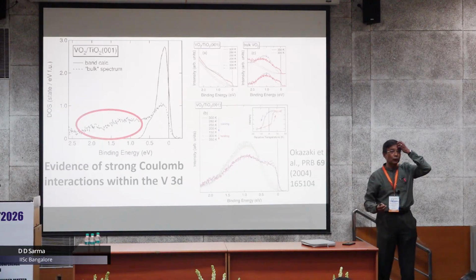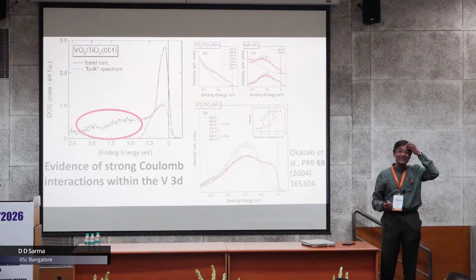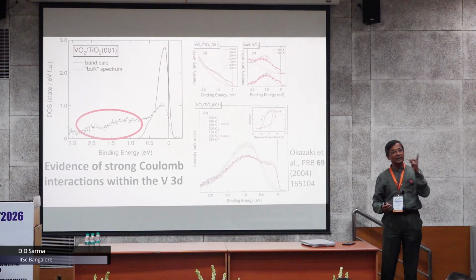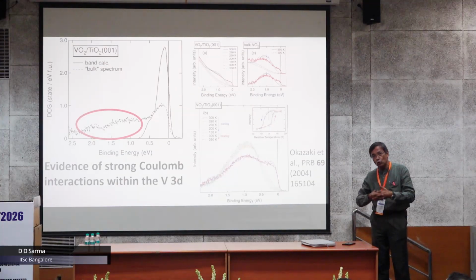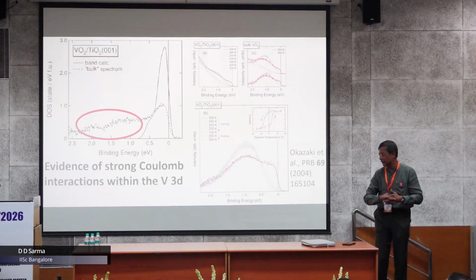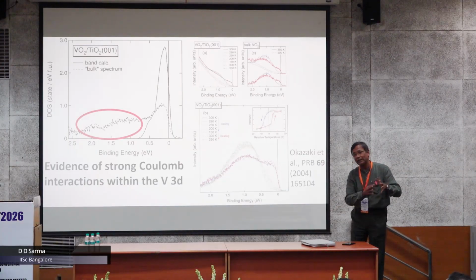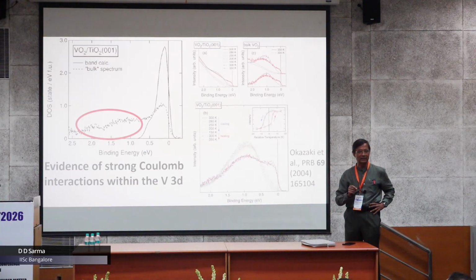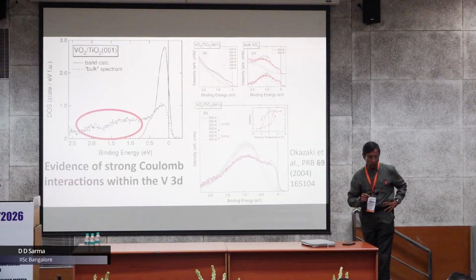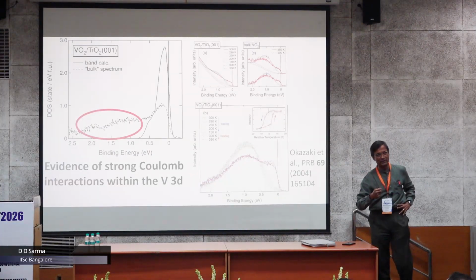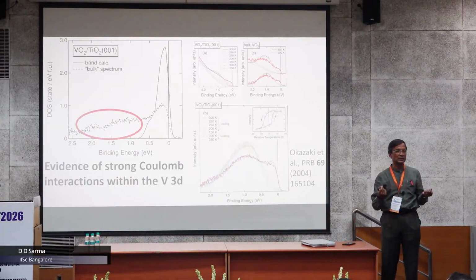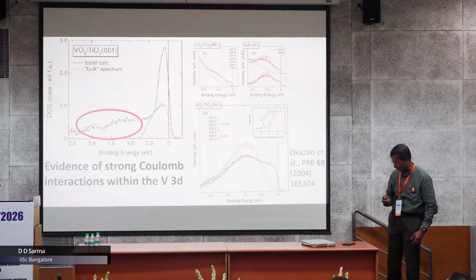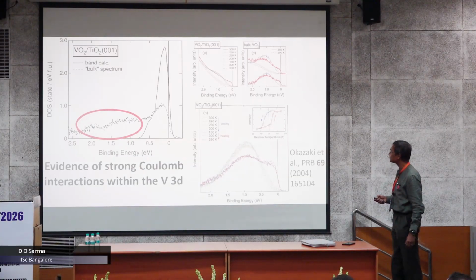Of course, the 1994 paper didn't make it as clear that for this M1 phase, if you do a true, honest density functional calculation as well as you can, in the approximations that were available at that time, one didn't get an insulating state. One got a very small overlapping metallic state with a small negative band gap, as it is sometimes called, basically almost like a semi-metal. So it didn't drive it all the way to the metal-insulating state.